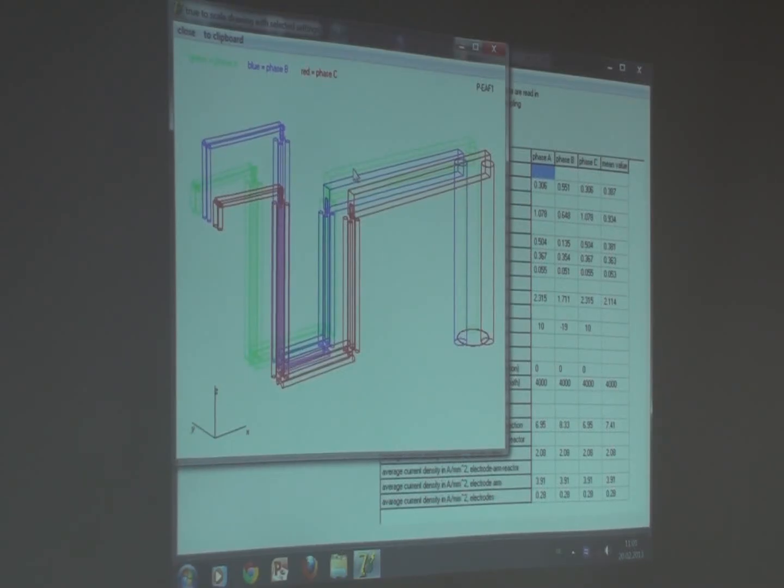And this is the reason why it is not good to work with a furnace with an unsymmetrical system. I'm telling this because all of the design of these systems has the idea of what I can do to make a symmetrical reactance system. This is the reason. Is that clear? Yeah. It's okay?